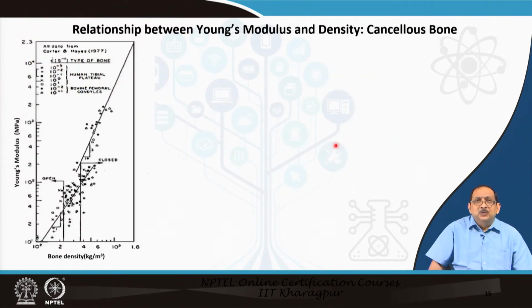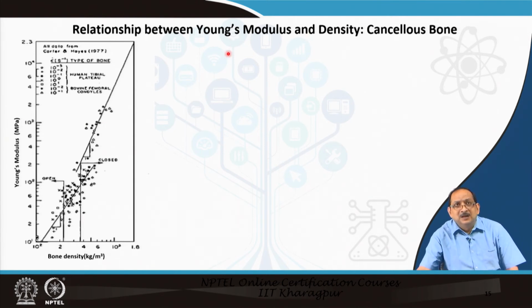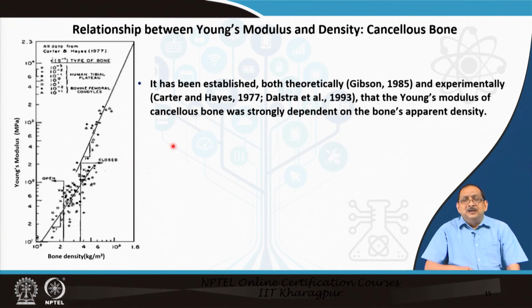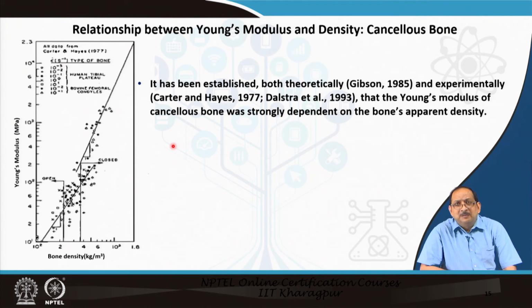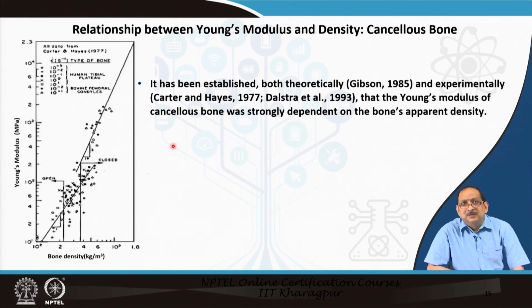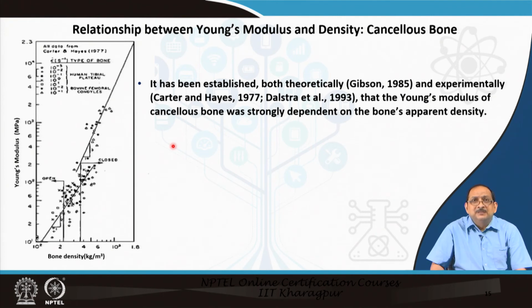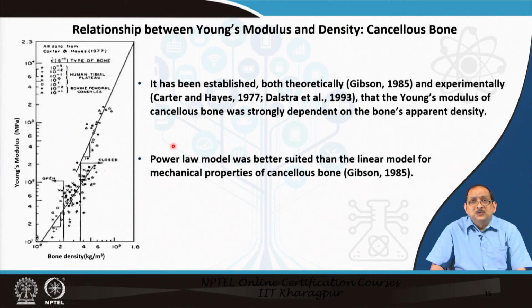We continue with the relationship. As you can see on the left, all the data tested by Carter and Hayes has been plotted. Later, L.J. Gibson from MIT actually fitted a relationship based on this experimental data. So, it has been established both theoretically by Gibson and experimentally by Carter and Hayes as well as Dalstra, that Young's modulus of cancellous bone was strongly dependent on bone apparent density. Power law models were definitely better suited than linear models, which were suggested years earlier, for mechanical properties of cancellous bone.